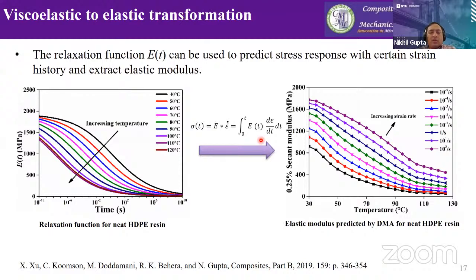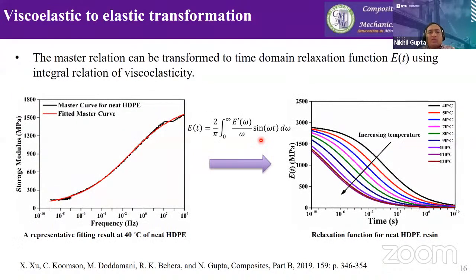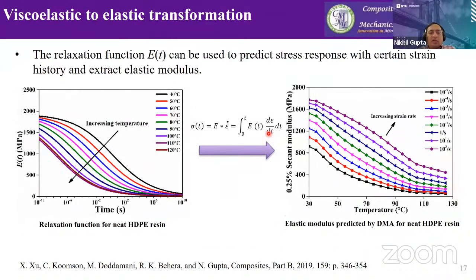So based on the equation that we had selected here for the relaxation function and the integral that we get here, this integration is conducted partially numerically because the equation is a convolution and it's not possible to get the direct integration of that easily. So this numerical way provided us with a method to capture the integration more easily. So that exercise we can do for various pivot temperatures, and eventually we can get the elastic modulus out at various strain rates and temperatures. So this exercise gave us the elastic modulus, and in this case, we captured the secant modulus because there's no straight line portion in the stress strain graph.